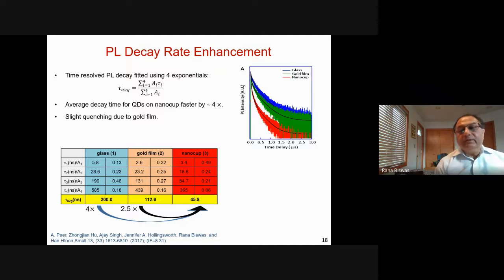So these are the first measurements of the photoluminescence decay as a function of time for the glass in blue, the gold film in green, and the nanocup array in red. And you can immediately see that the decay rate is much faster in the nanocup array. And in this field, it is usual to fit these decays by 4 exponentials, and the details are just listed over here. And you see the average decay time in glass 200 nanoseconds, gold film 112 nanoseconds. Sorry, nanocup, it's about 46 nanoseconds.